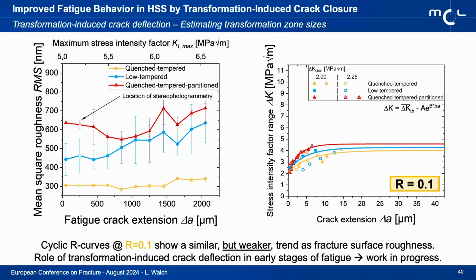And if you compare it to the actual fatigue results, here an example of just the cyclic R-curves, you can see that the ranking or the trend really seems to be in quite nice agreement.